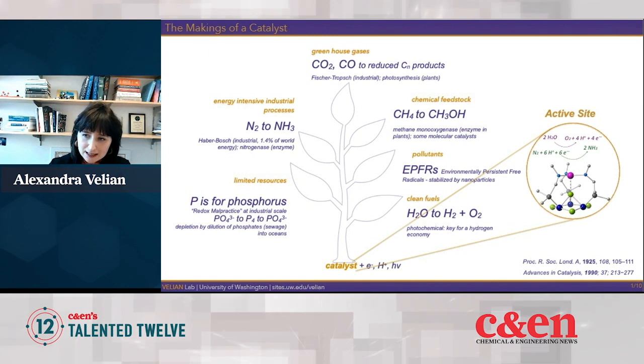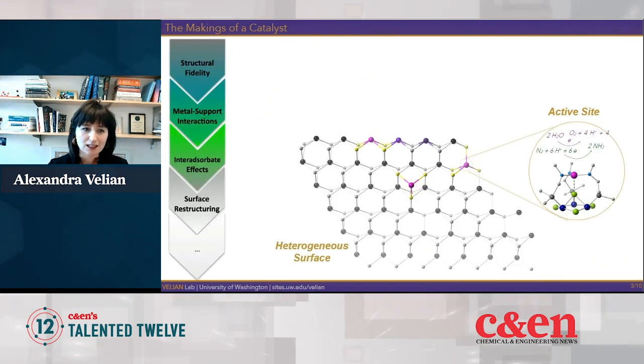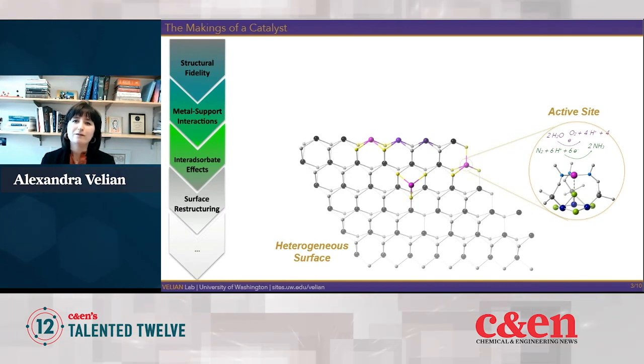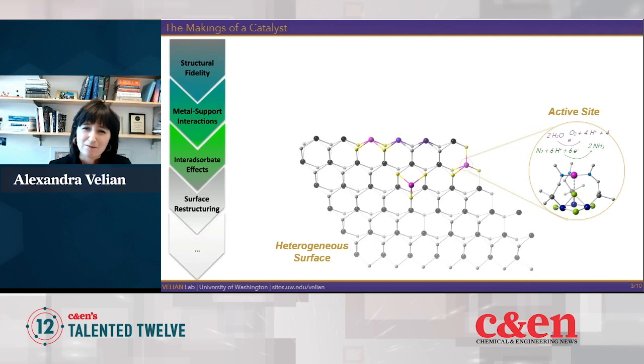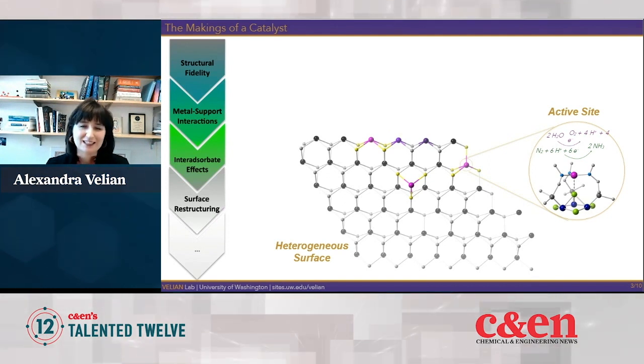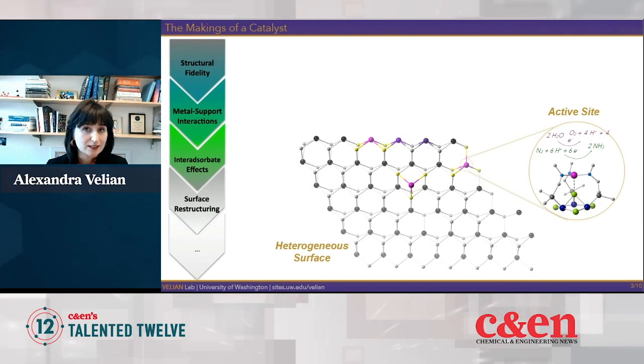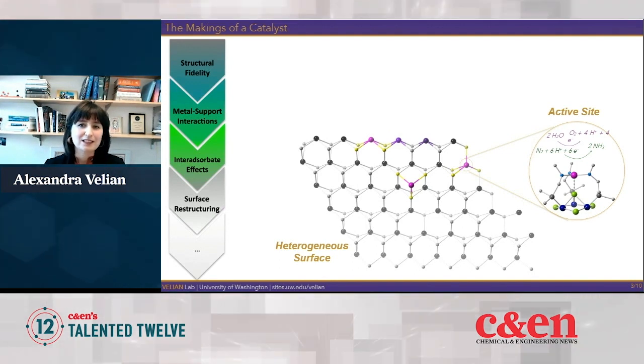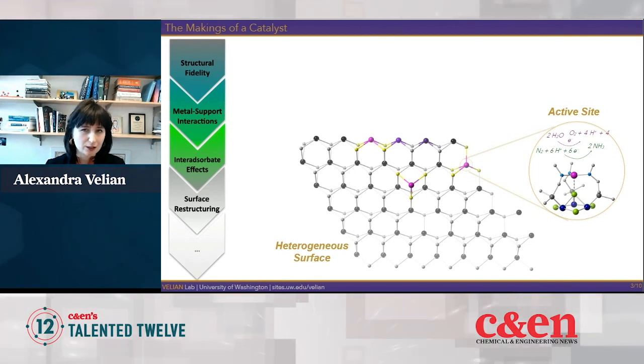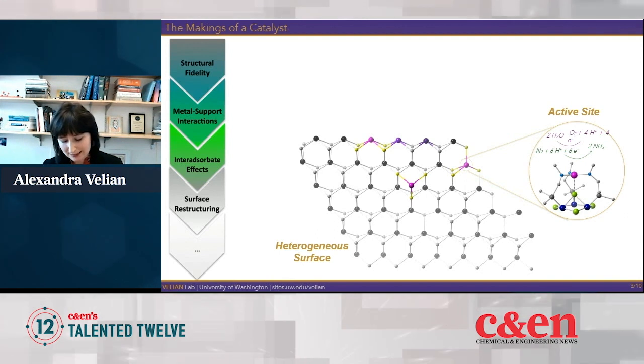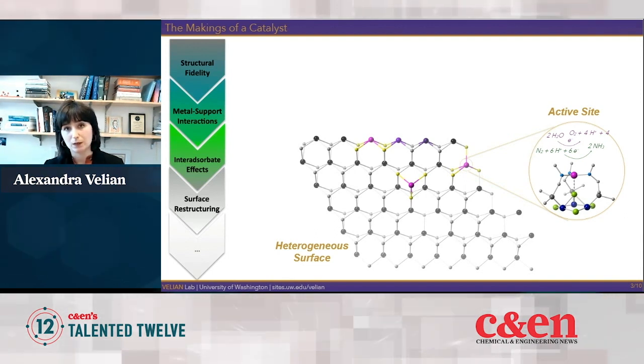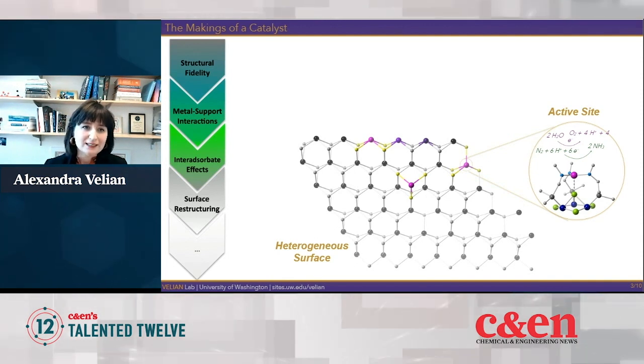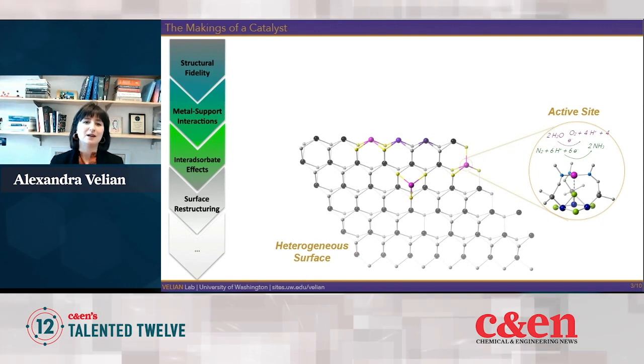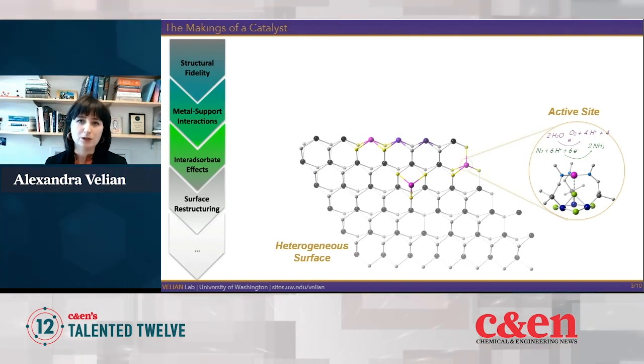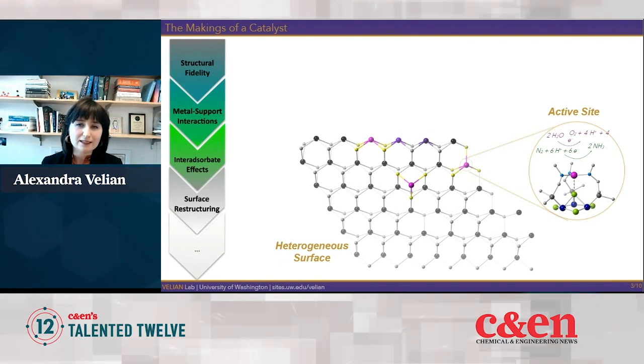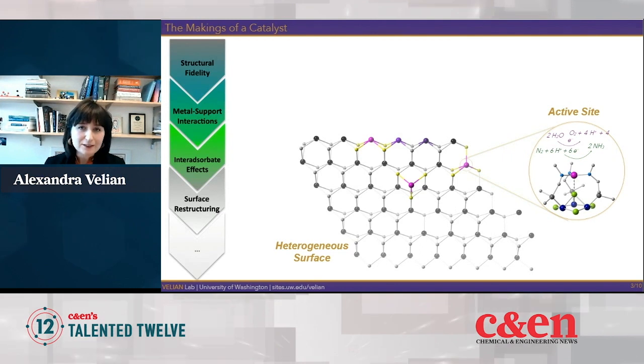So if we consider a typical catalytic heterogeneous surface, we find that not all of the exposed sites are catalytically active, typically. The concept of active sites was introduced about 100 years ago by Taylor, and it reflects experimental evidence that many catalytic surfaces are not uniformly active. And so they exhibit activity at sites that are distinguished by special coordination environments, typically low coordination. However, in typical catalysts, we find that there are a multitude of ill-defined and varied active sites, and this can be detrimental to their selectivity, for example.